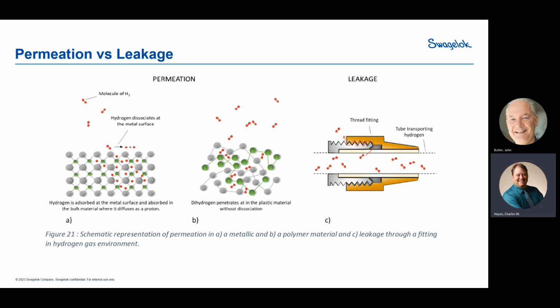Now, there's something else, and it happens in rubber. In rubber, what ends up happening is the dihydrogen actually penetrates as dihydrogen. So it'll get inside the rubber or plastic materials. It'll diffuse through them fairly quickly, and that permeation means that it can move all the way through the material and out the other side. So the problem with using polymers and elastic materials is that you can't have a very, very limited and low leak rate because it's constantly moving through that material. That structure is much different. You notice the grain structure and crystalline, organized structure of metals and a very disorganized structure of rubber materials. And what the hydrogen can do is follow in there.